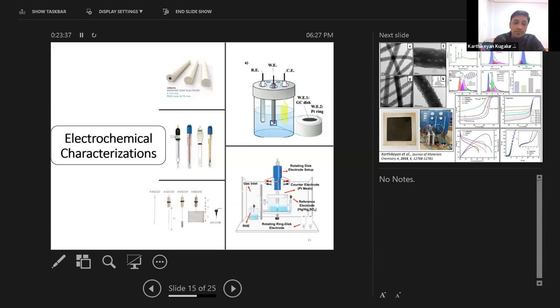These electrodes will be immersed into the electrolyte, and your catalyst material, which you are developing using platinum supported carbon nanofibers, will be directly deposited onto the working electrode and will act as the working electrode. You will have the silver chloride reference electrode, and the counter electrode will be platinum. There are three different kinds of working electrode: carbon, gold, and platinum. Mostly we will be using a carbon rod based working electrode. There are several kinds of reference electrode, of which we are using silver chloride, and platinum wire or platinum mesh will be used as the counter electrode.